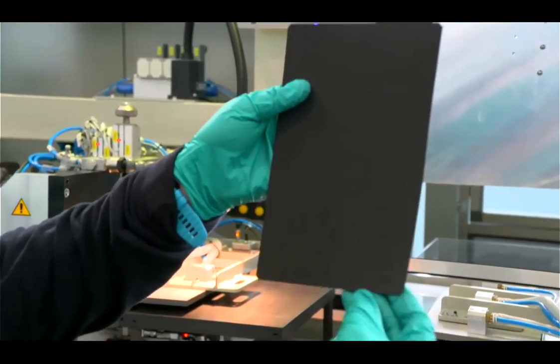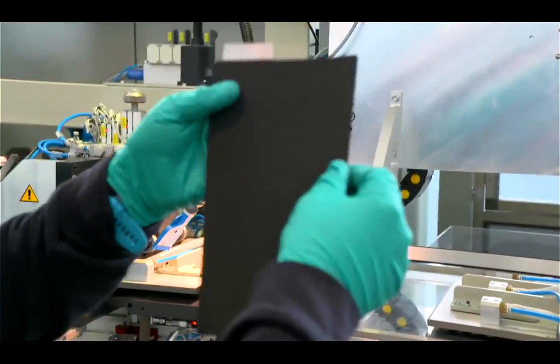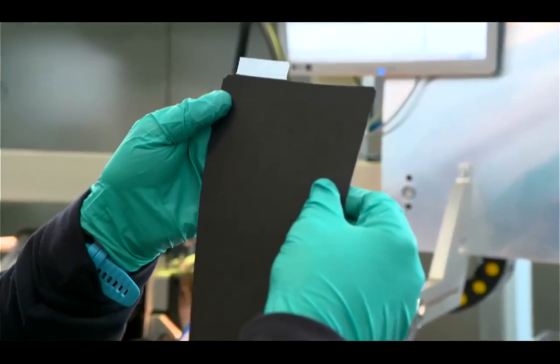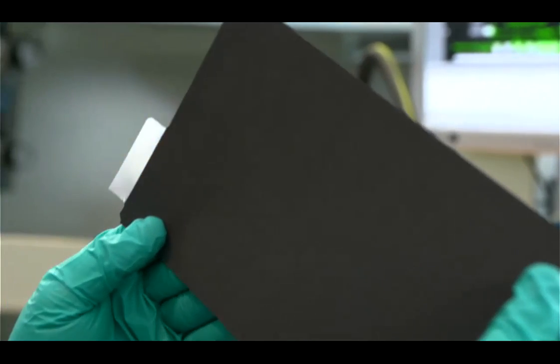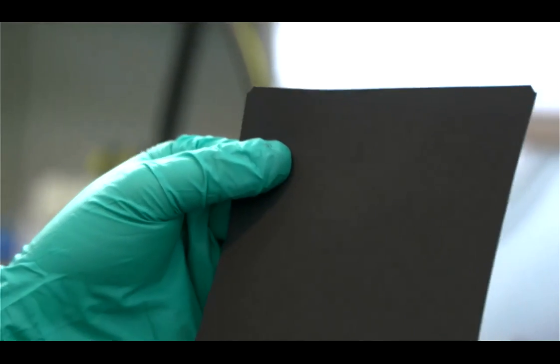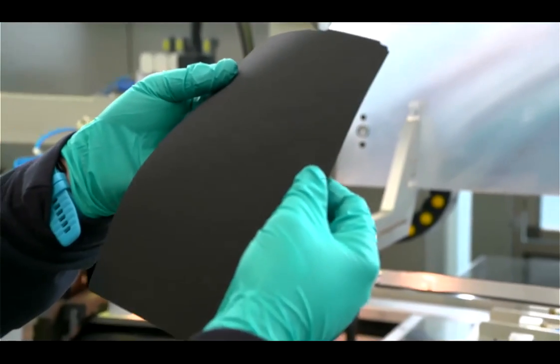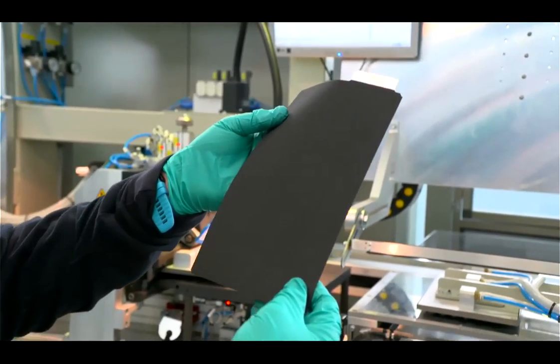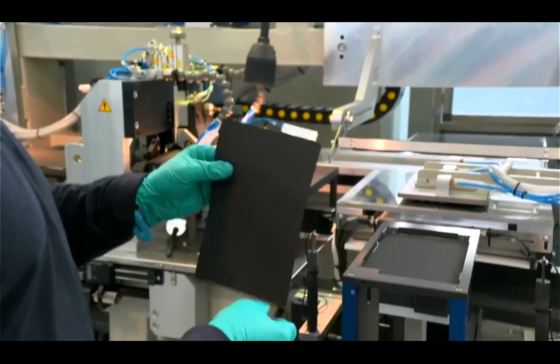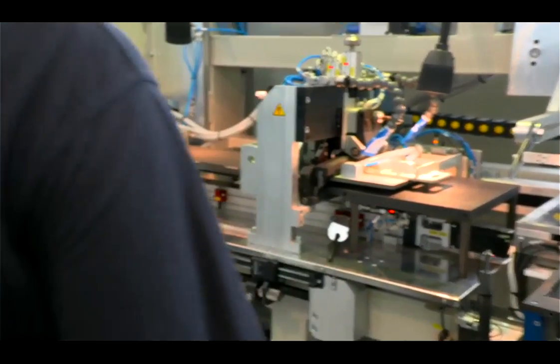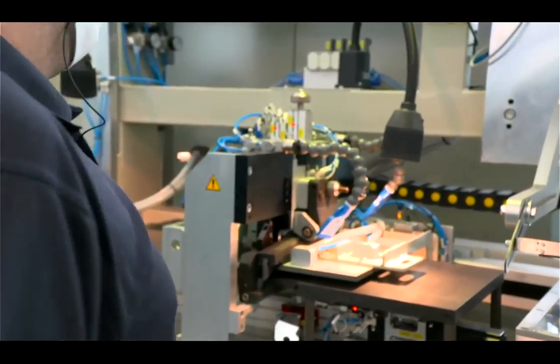We can go to the corners and the edges. We can see that they are cut very clean. We cannot see any particles coming out from the electrodes. Actually, when he's bending the electrode, you can see the good quality of the electrode. That means the adhesion of the electrode to the current collector is quite good, because you are not seeing any delamination. That is something that we optimize in the lab part,